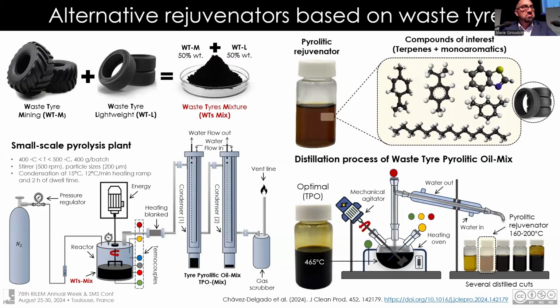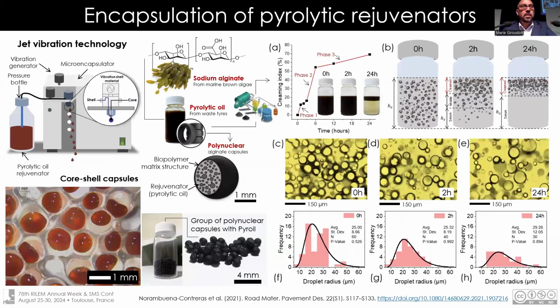This is my favorite research. Basically, we can use end-of-life tires and thermochemical conversion, for example, pyrolysis, to produce a specific rejuvenator, specific liquids, in specific components. In the lab, you can increase, using different chemical approaches, the terpenes and monoaromatic components inside the material in order to stimulate the specific molecules inside the asphalt. That is possible. At the same time, it's possible to encapsulate these rejuvenators using biomaterials.